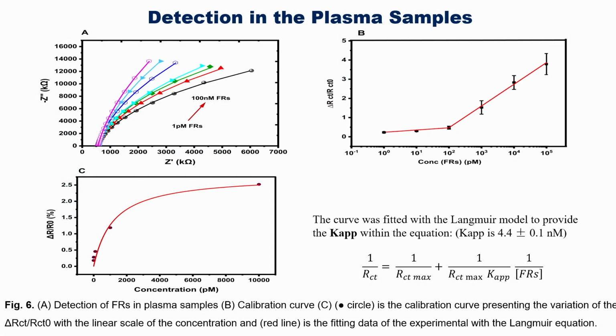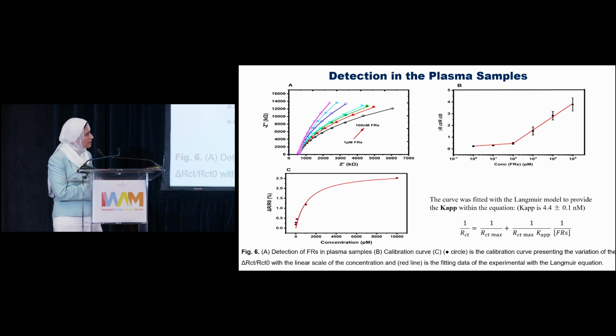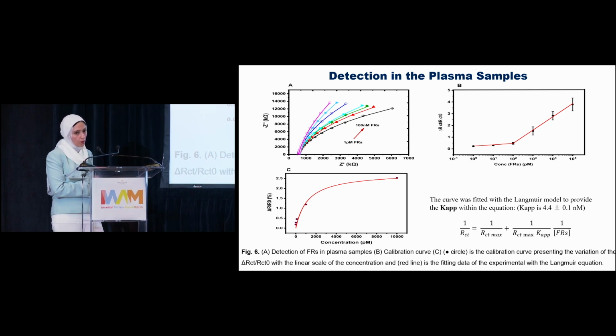As we see from the calibration curve, there are 2 slopes. This may be due to the many binding vacancies in the structure of the nanofibers, which allowed the reaction between folic acid and folate receptor at low concentration, and the remaining folic acid in many binding sites in the nanofiber structure allows the reaction at higher concentration. Here I want to point out that the limit of detection was about 0.1 picomolar. It is the lowest limit of detection relative to the published articles for the same biomarker, and a 25-fold enhancement relative to our last publication.